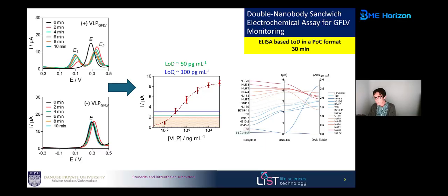We compared the results with the only commercial sensor for this type of plant virus, which is a DAS ELISA from Bioreba, which is based on absorption. And we compared it with our sensor based on currents. If you correlate these different samples, the control worked very nicely, so no signal. And from all these different samples we had an agreement of 100%, besides one, this T58, which gave a very high signal in the DAS ELISA, and a very small signal in our electrochemical sensor.